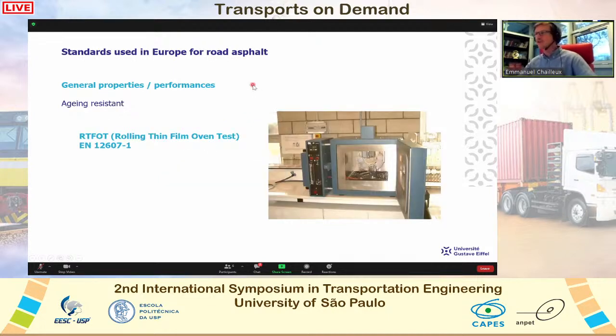For the aging, in Europe we just use for specification the RTFOT, the rolling thin film oven test, where air is blown across a film of bitumen in some bottles during a certain time at 163 degrees in order to reproduce what happens during the mixing process in the plant.